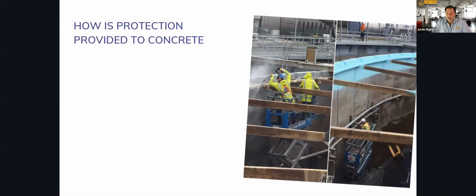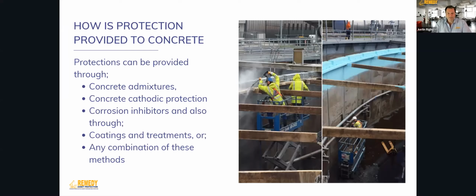So in dealing with carbonation and salt ingress, there's a range of different methods that can be employed to protect the concrete. And that includes, at the design phase, including concrete admixtures in the mix. Cathodic protection can be applied, but usually in the early years of a structure, if the designer puts some tags and probes in there, you don't need cathodic protection, but the tags and probes enable you to monitor corrosion of the steel. And then down the track, when you need to apply corrosion protection, you know when it's due, whether that be in 5 years, 10 years, or maybe 15 years, you can start applying cathodic protection to make the structure last longer.